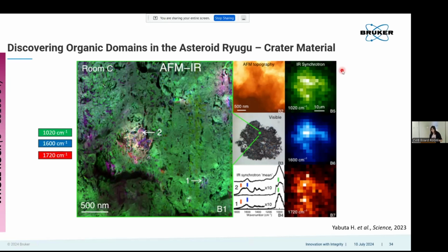And so when they cut these very thin, they then send them to researchers around the world to characterize. In particular, this one went to a synchrotron first, where they looked at the infrared map of the functionalities. And what they see in this material is similar to what we're going to look at. You see the larger matrix in green, but then you start to see the PAHs located in one location, and then the carbonates in another location. And then we're going to drill down on the areas that are particularly bright here.